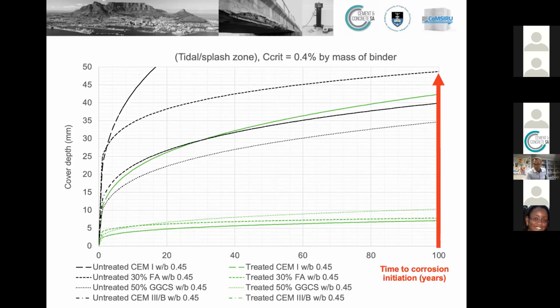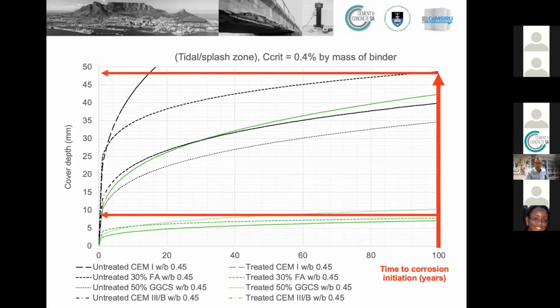If we look at the values that we calculated for the treated concretes, we only need a cover depth of 10 millimeters. Now, I'm not advocating that we should build concrete structures with 10 millimeters cover, but I think what this shows is that instead of using 50 mil cover, we could possibly get away with 30 mil cover or even 25. Or we can look at concrete structures that have been constructed with too low cover or too low concrete quality and use hydrophobic coatings as a treatment to still achieve durability